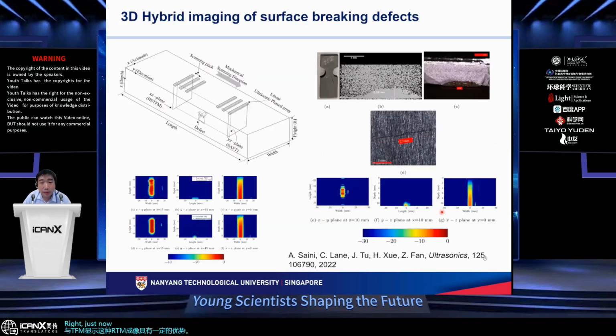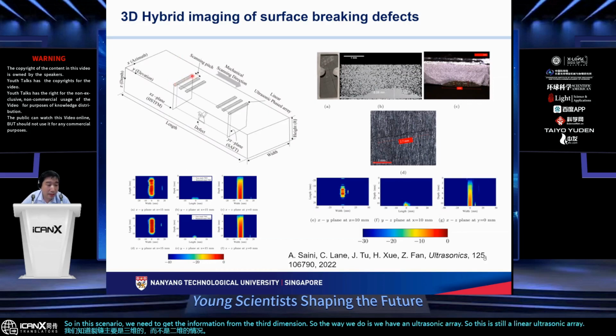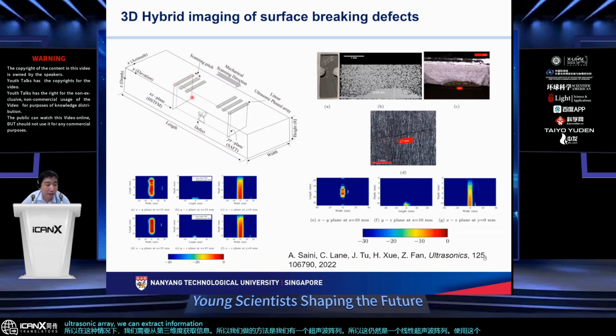Right. Just now we were talking about defects that are more about two-dimensional defects, but we can also use our ultrasonic imaging for three-dimensional defects, because we know that cracks are mainly three-dimensional, not the two-dimensional case. So in this scenario, we need to get the information from the third dimension, right? So the way we do it is we have an ultrasonic array. This is still a linear ultrasonic array, and using this linear ultrasonic array, we can extract information from this plane. In this plane, we use the traditional half-skip total focusing method to get the information.